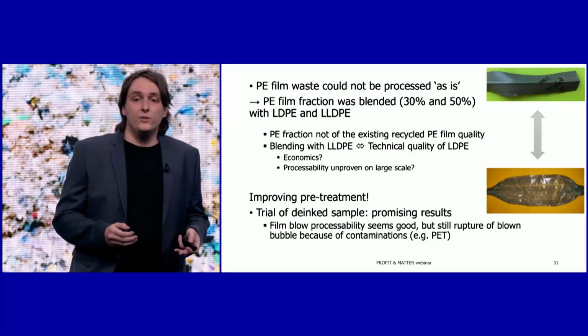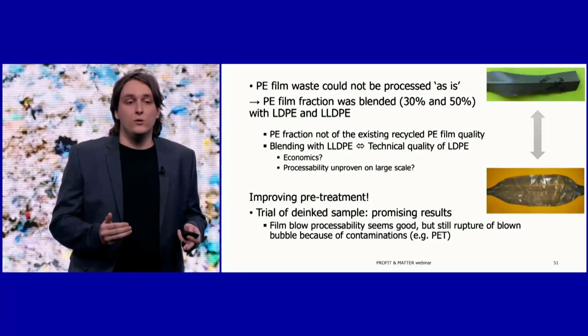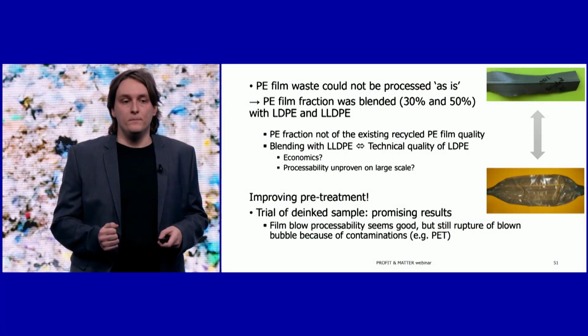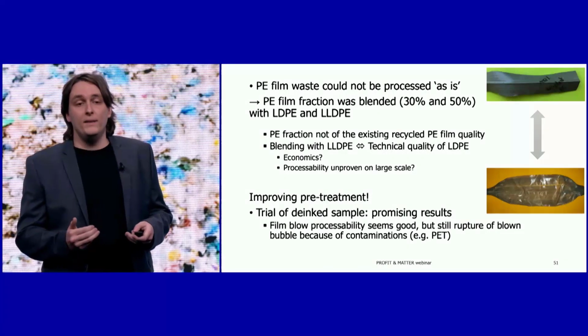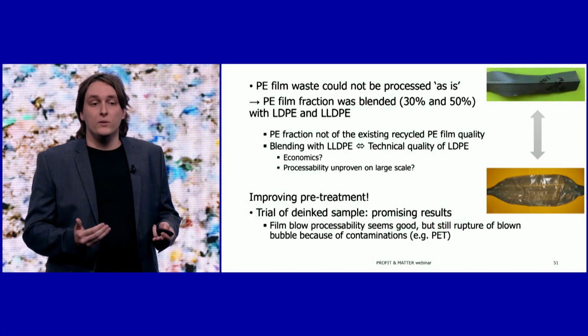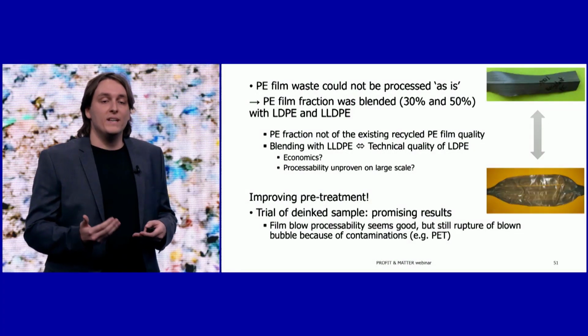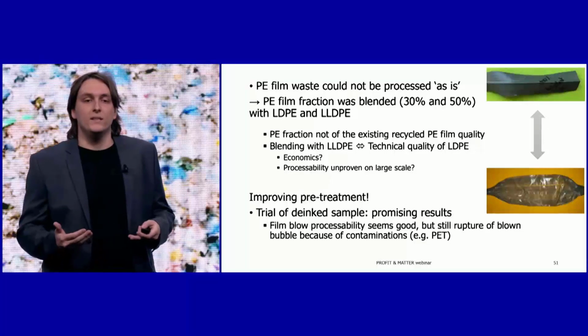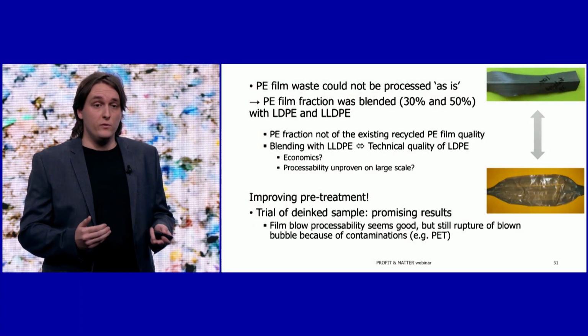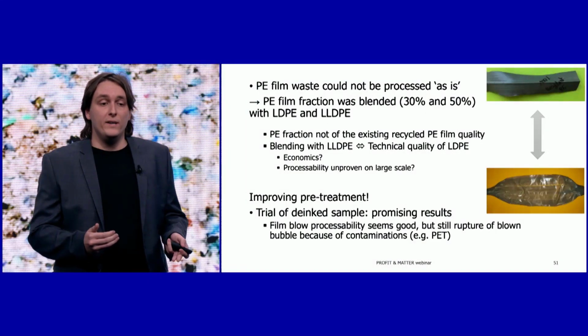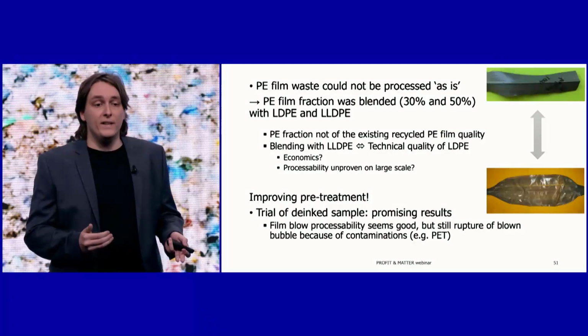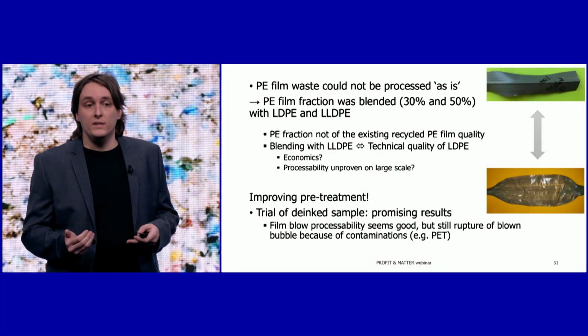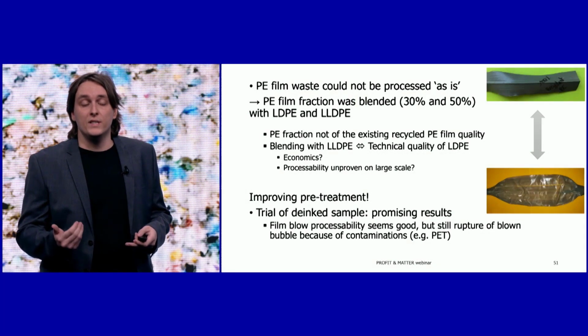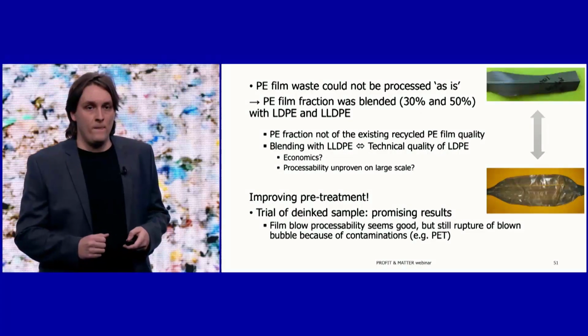So we can conclude that the PE films could not be processed into the existing recycled PE film quality. But we can consider blending with LLDPE, and in this way we can achieve a technical quality comparable to an LDPE polymer. Of course, it has to be verified whether this is cost effective, and also the processability to uniform film on a larger industrial scale is important.